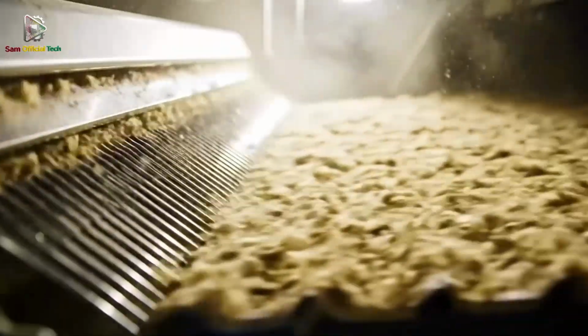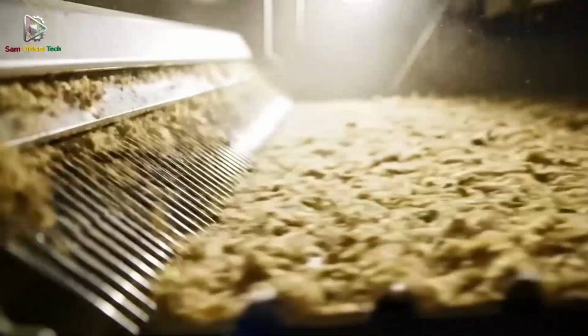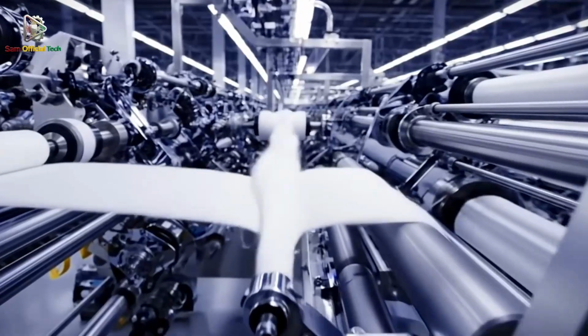Embossing creates the grain pattern. Heated emboss rollers press a texture into the coating under controlled pressure and temperature. If pressure is uneven, the grain depth varies across the roll, and that inconsistency becomes obvious on small wallet panels where every piece sits side by side in a retail display.